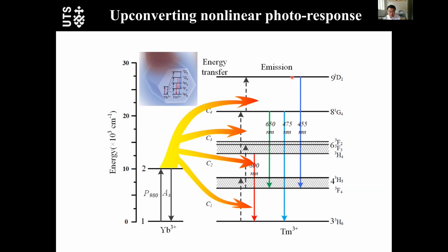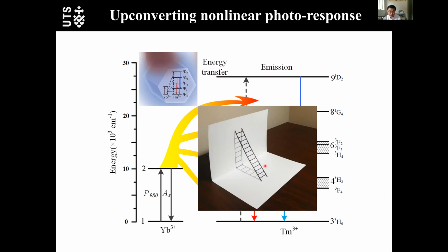After this, the emission comes out from all the different energy levels. The reason this has really high upconversion efficiency is that it has many levels. Each of these real levels is a metastable state, so the carrier has a longer lifetime in each level, waiting for another carrier to come in and pump the energy to another level. It's just like climbing a ladder. In a traditional two-photon absorption, you don't have these real levels, so your chance is really low. But for this one, because there are many real levels, the chance is really high. This is why this nanoparticle has high upconversion efficiency.